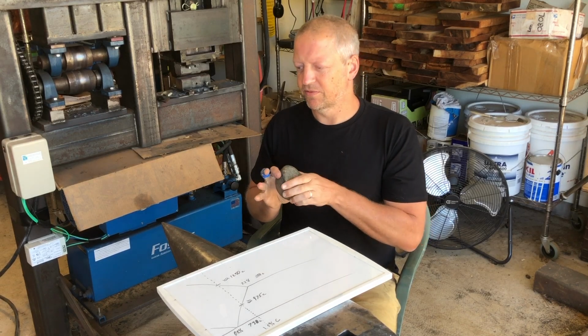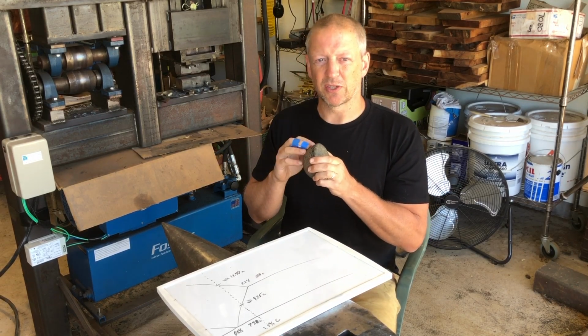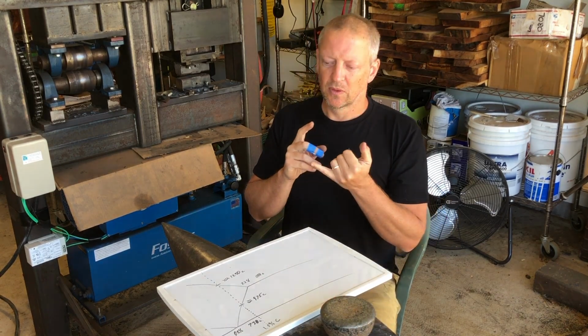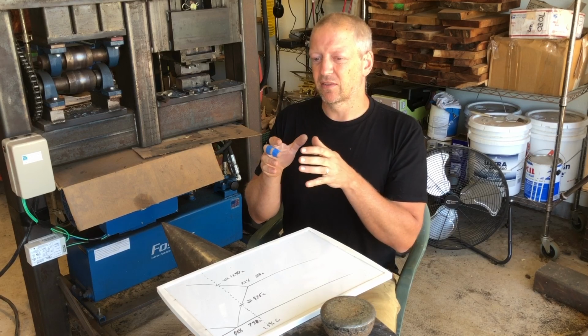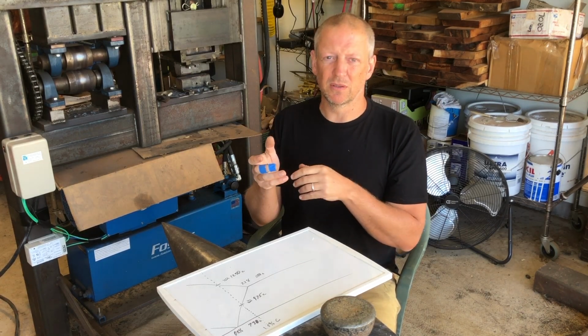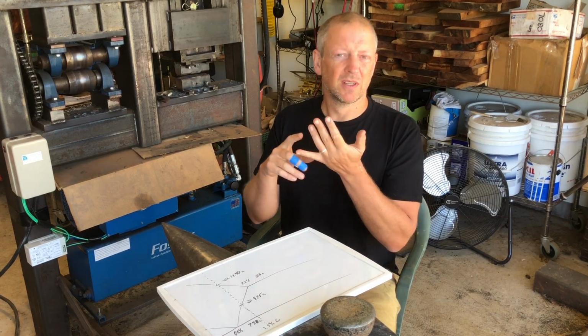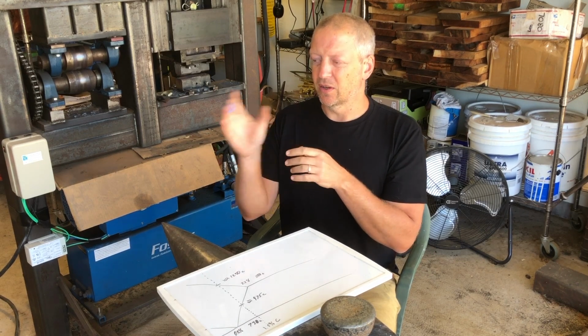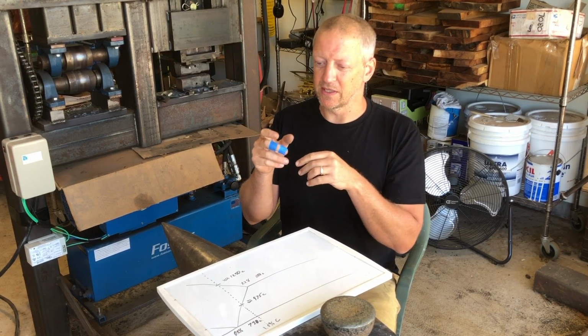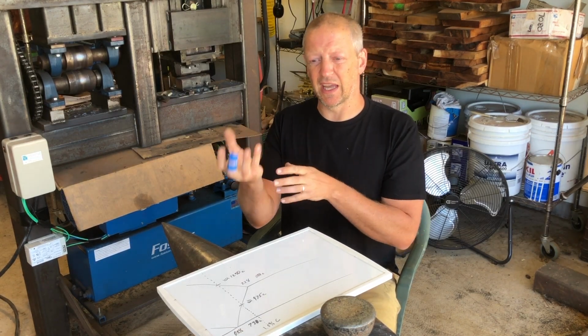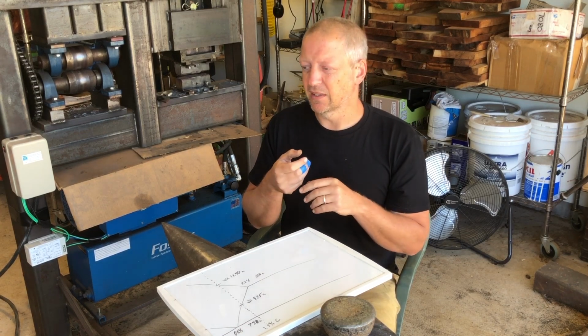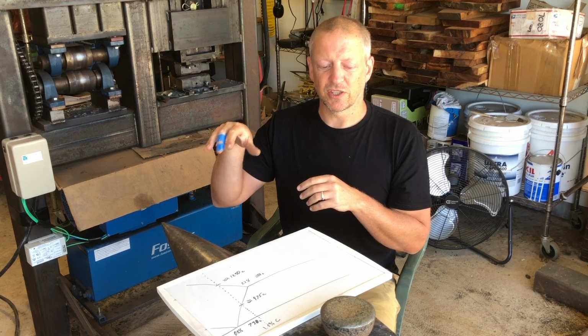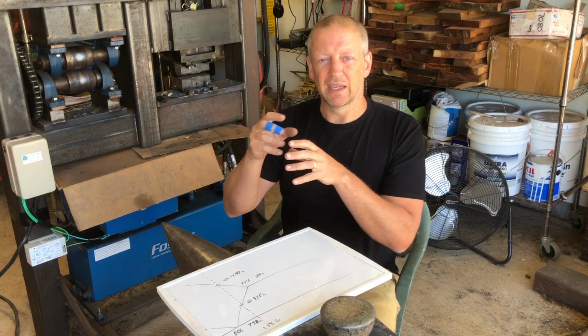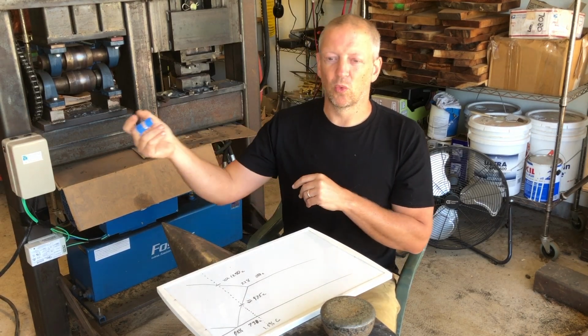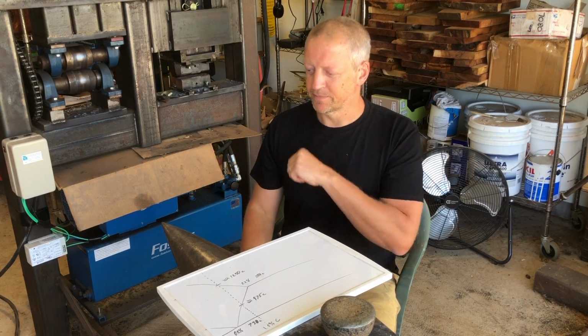And there are a couple good reasons for a process that works in that fashion, especially historically speaking. One, probably the most important reason is that the historical ingots would have been quite variable. The carbon content would have been quite variable. Many times the smiths, actually in almost all cases, the smiths were not making the ingots. They were just getting the ingots, purchasing them, and then forging them. And there were a number of different locations where ingots were made. So you might be getting ingots from different places depending on where the latest trade had come from.